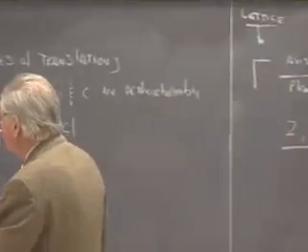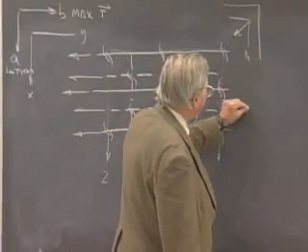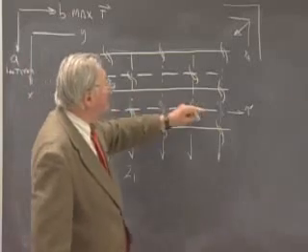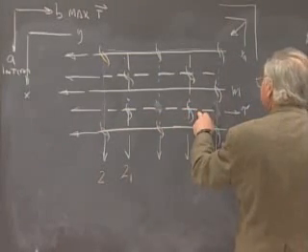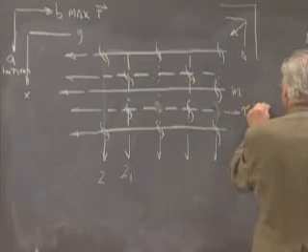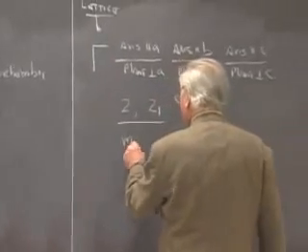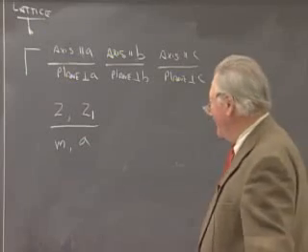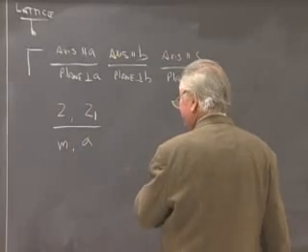And if we look at the planes that are perpendicular to A, there's two of them. There's a dashed line, and this is a glide where the direction of tau is in the plane of the paper, so that we're looking edge on at the glide plane and perpendicular to tau. And then there is a solid line, that's the symbol for a mirror plane. This would be a glide in which tau is along B, so this is a B glide. So those are the two sorts of symmetry planes that are perpendicular to A. Again, there are two of them. So we could put in either M or we could put in A for the plane that is perpendicular to A. So already there are four different possibilities for the first character. So obviously what I'm leading up to is the fact that we're going to have conventions of necessity to come to a symbol on which everyone agrees.